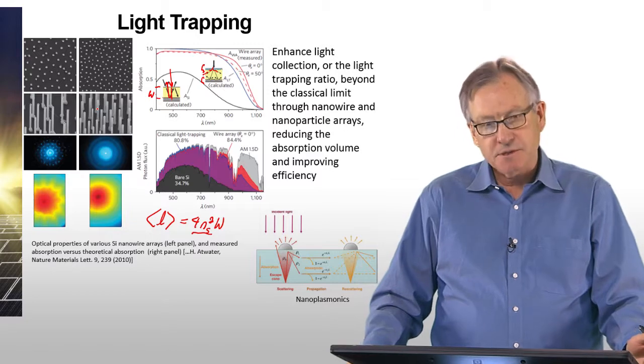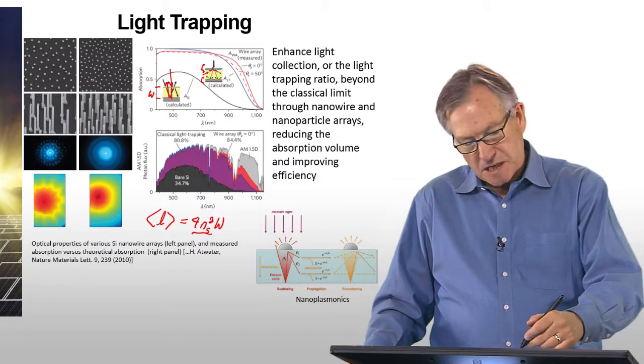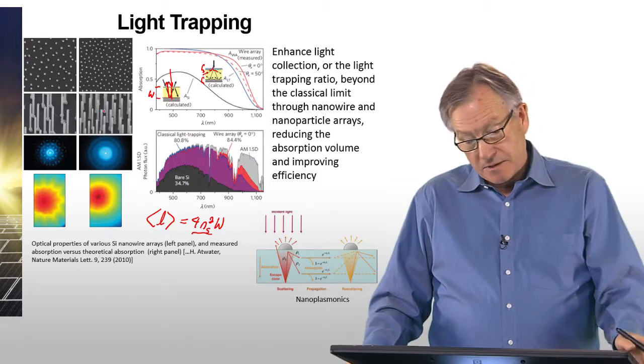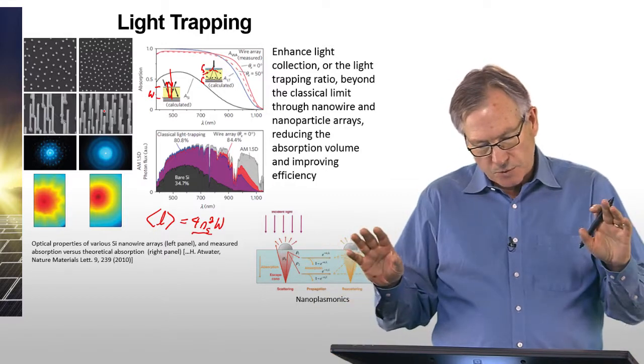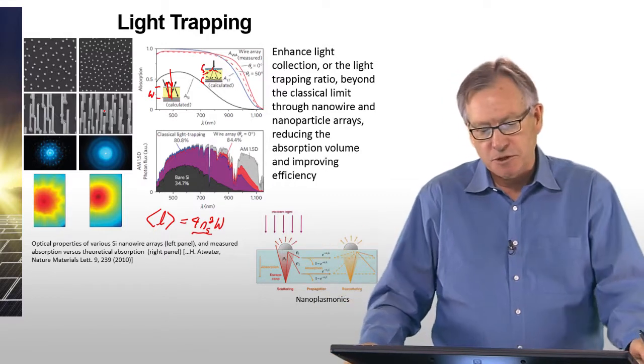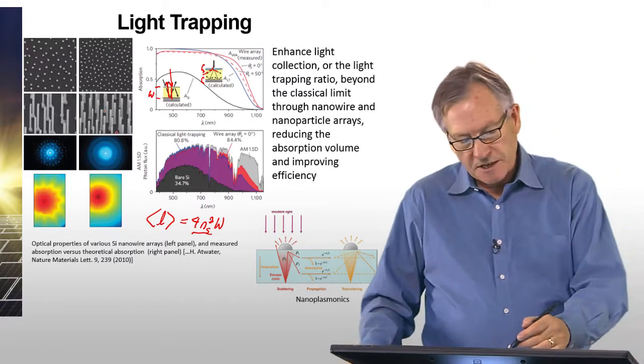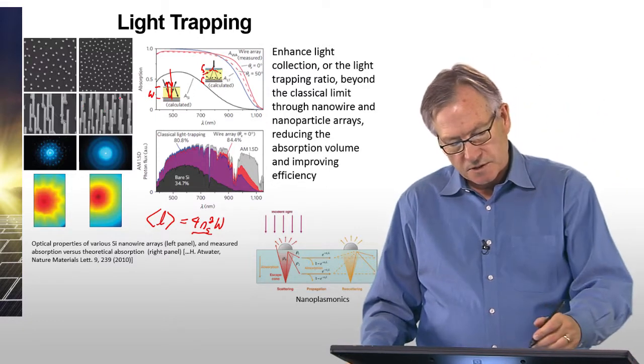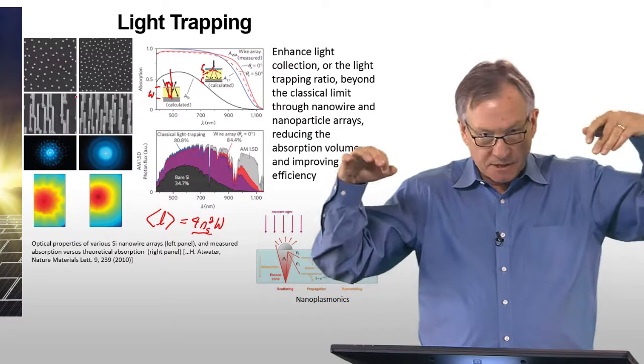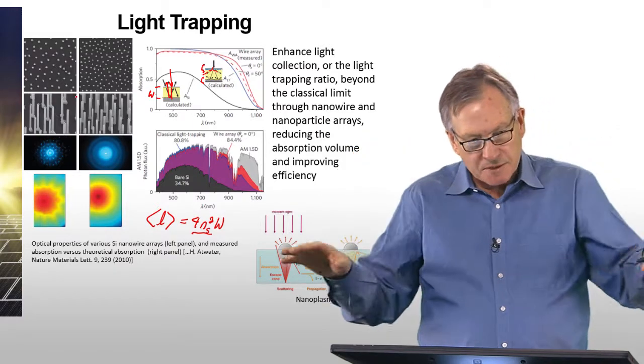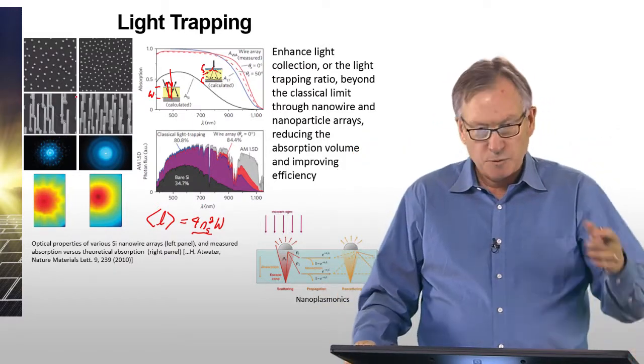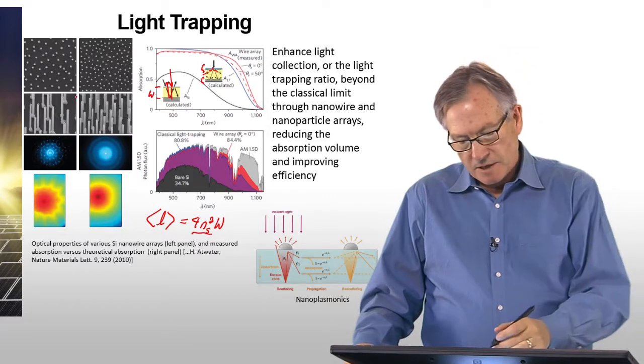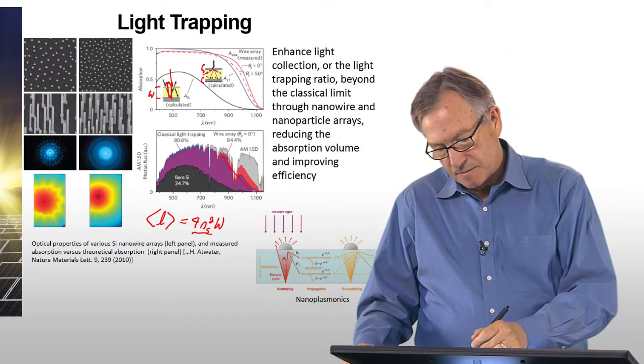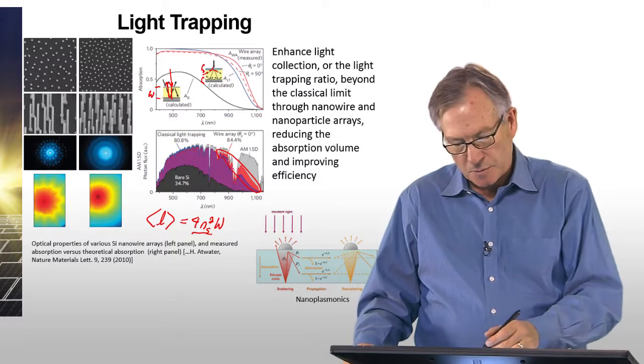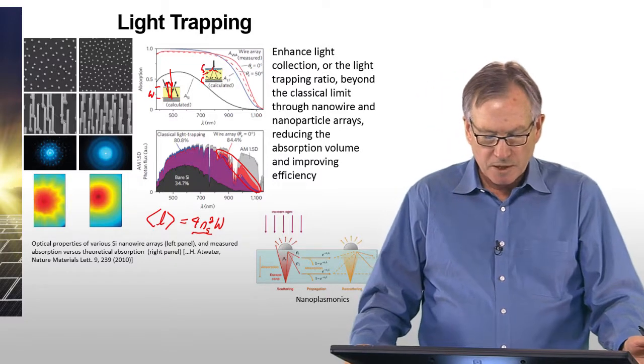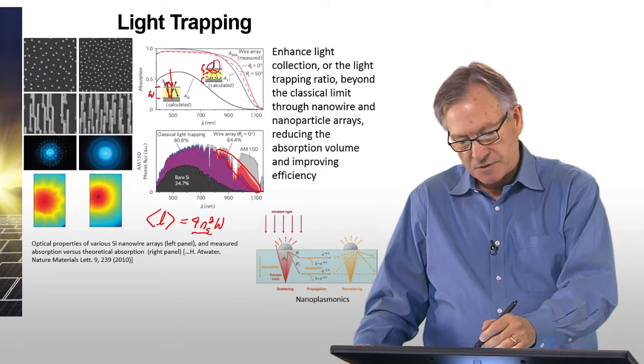And these nanowires act, you can think of it as acting, as little antennas. They actually form, in one sense, a photonic band gap structure, which I'll talk about. But in any case, this forest of nanowires captures the light, traps the light inside, and leads to more absorption. This picture illustrates, the purple represents the enhancements you have from classical light trapping due to having a rough surface.